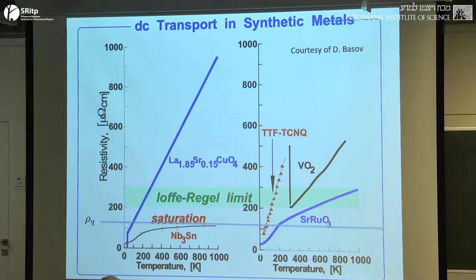Here's a quasi one-dimensional organic charge density wave system, TTF-TCNQ, again with a nice linear temperature dependence of the resistance that doesn't seem to pay any attention at all to the quantum of resistance. This is strontium ruthenate, but not that strontium ruthenate, and also not that other strontium ruthenate. This is the cubic infinite layer strontium ruthenate that has a ferromagnetic transition at around 150 Kelvin, below which it becomes a reasonably good metal, and above which it has this T-linear resistance, which doesn't seem to saturate.